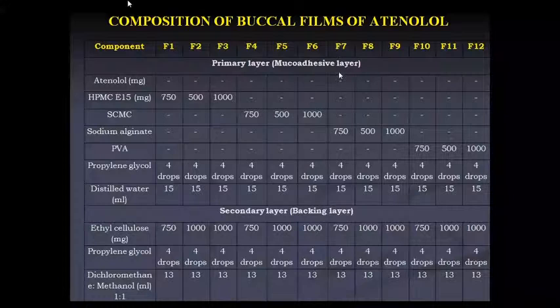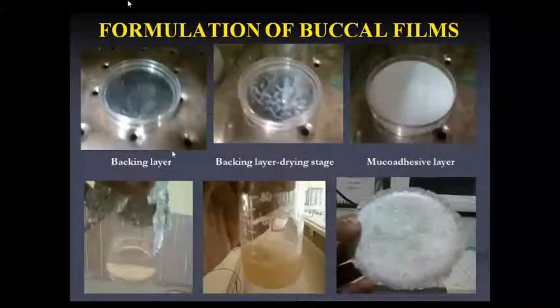Next, look here at the secondary layer. The secondary layer uses ethyl cellulose. This is a hydrophobic polymer, which is not soluble in water, so it can make the backing layer of the film. You can look at this picture and easily understand. See here, this is the Petri plate. I use the Petri plate with mercury as a substrate. Look here at the clear solution of the backing layer: ethyl cellulose, a hydrophobic polymer, dissolved in dichloromethane and methanol, organic solvents, to make a clear solution. Then this clear solution is transferred over the mercury substrate. You have to wait a few hours. After evaporation of the organic solvent, it makes the film like this. So this is the backing layer we already made.